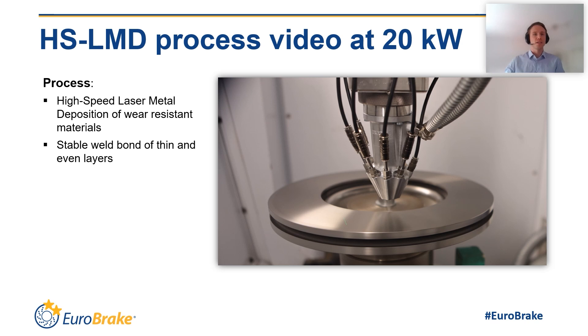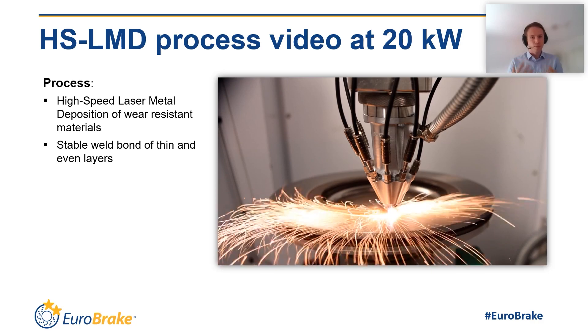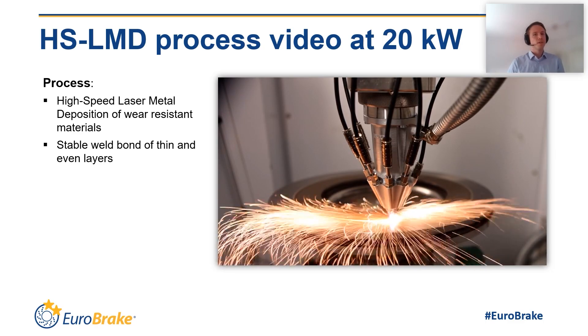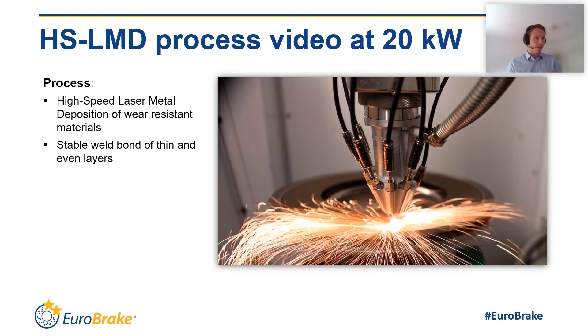The task of high-speed LMD is, to put it in one sentence, enabling the serial production of brake discs that have a significantly reduced wear, but still meet all the requirements and quality aspects of brake disc manufacturing. In the process, a very thin layer of hard steel material is sprayed on the disc at high speed. For good economy and functionality of the final discs, the layers have to be very thin, have a stable weld bond, and of course have an excellent quality.